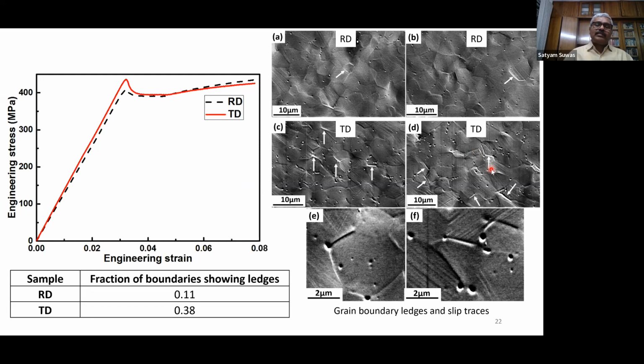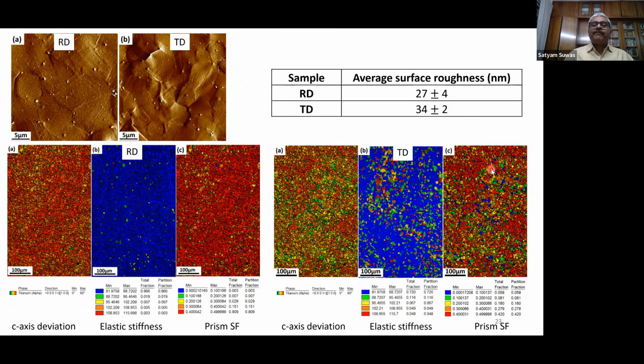So almost 4 times more ledges were observed in the case of TD samples. The roughness of the sample was also measured. All were polished initially to the same extent, but we could very easily see that the TD samples were rougher than the RD samples.